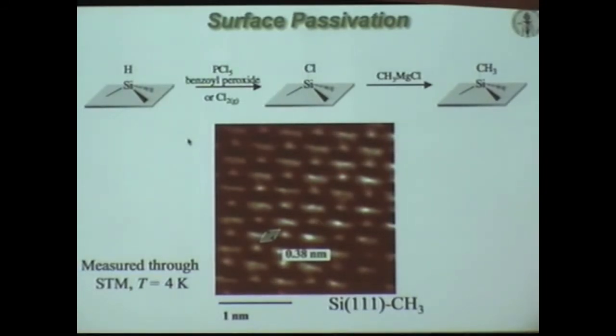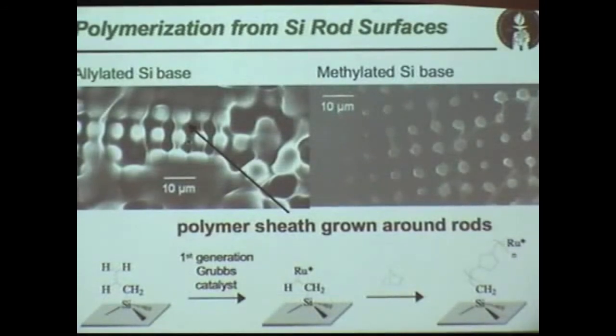This is an STM image at 4 Kelvin showing that methyl termination on top of the silicon 1-1-1 lattice. We can additionally grow conductive polymers this way by seeding them with a double bond on sites that aren't filled with methyl. We have Grubbs catalysts that then can ROMP double bonds and get both conductive and insulated polymer sheets as the top contacts around this bottom contact. In addition, we can laminate these materials. So instead of having to grow epitaxial growth of one phase on another, we just grow a piece of plastic and grow another piece of plastic and then laminate them together like making a driver's license.